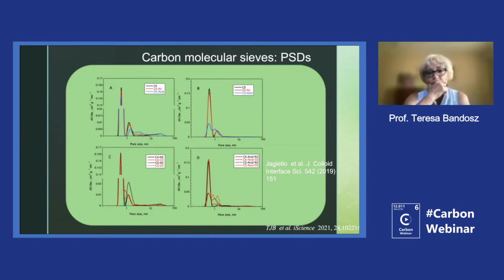Then after all of this, since very often it is considered that microporous carbons are not good for many processes because of the kinetic limitations for access of the molecules to the pores, we decided to look at carbon molecular sieves. We obtained two sieves from Supelco, the Carboxen and Carbosieve. And we modified those carbons, we oxidized them in air and in acid. Here you can see the distributions from nitrogen.